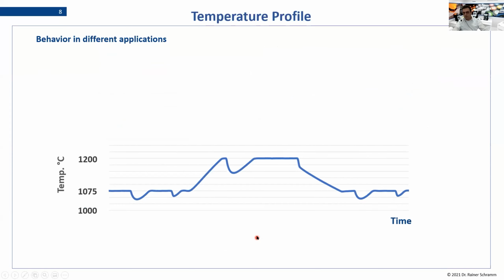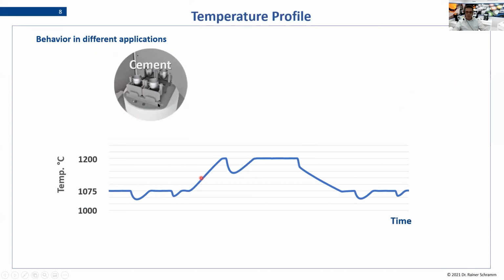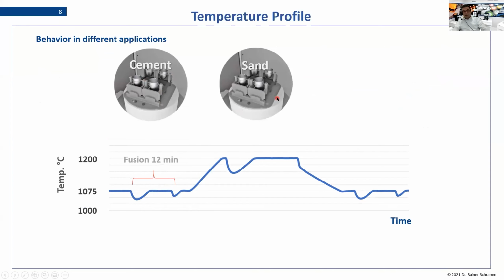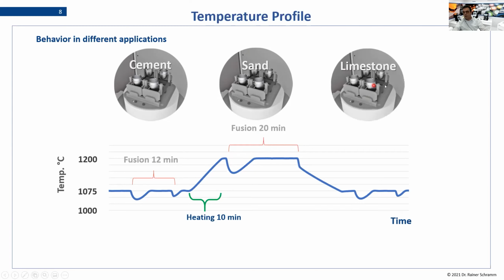But how does it behave now in different applications? So let us assume again our cement example. So we fuse 4 samples for cement for 12 minutes. Then you say, now I want to do sand. And this means we need a higher temperature. So automatically the furnace heats up to get the conditions for sand. Then the samples are introduced. If it's pure quartz, you would probably need a fusion program of 20 minutes. And after that, if you do a limestone, you cool it down again, and you will continue with the next fusion. So you see the system is able, fully automatic, to handle different applications, different timings, different temperatures, and this up to 4 different applications.